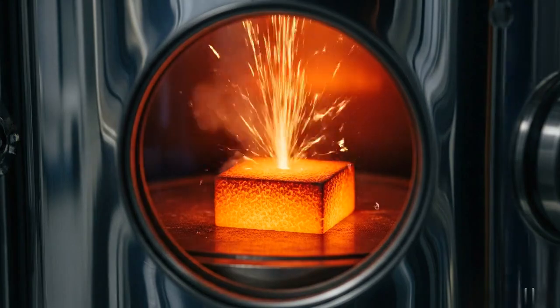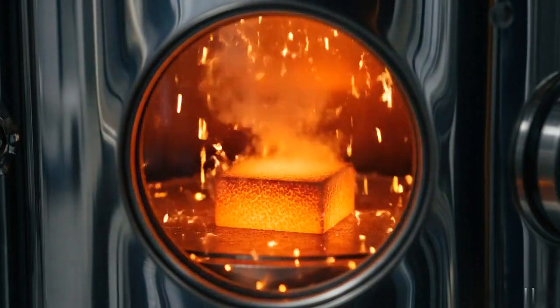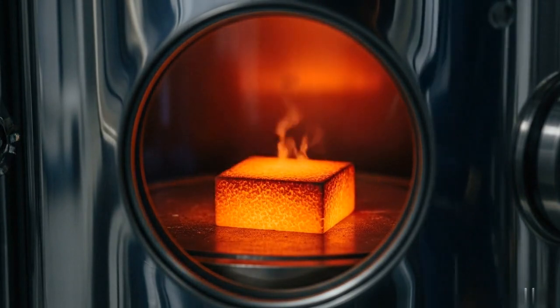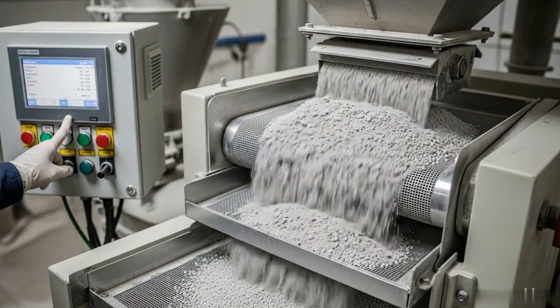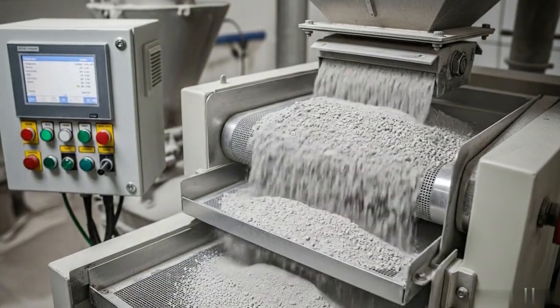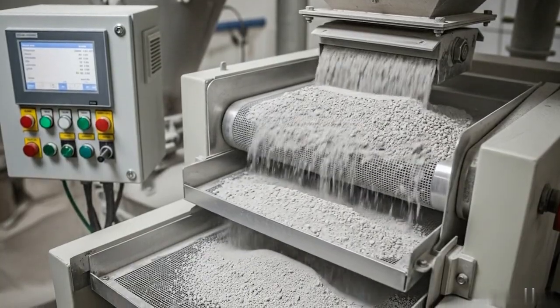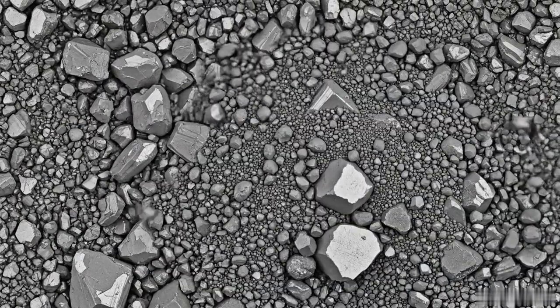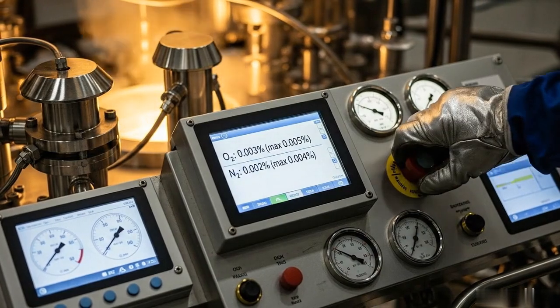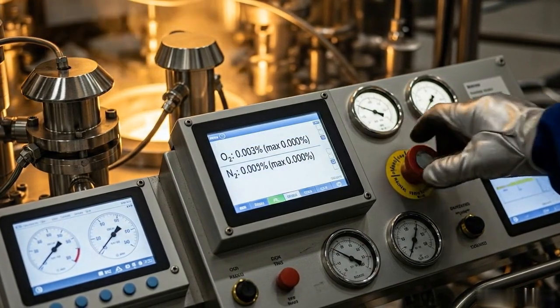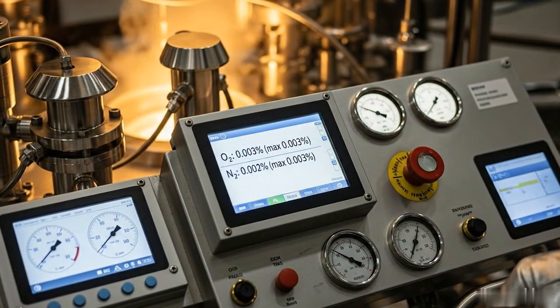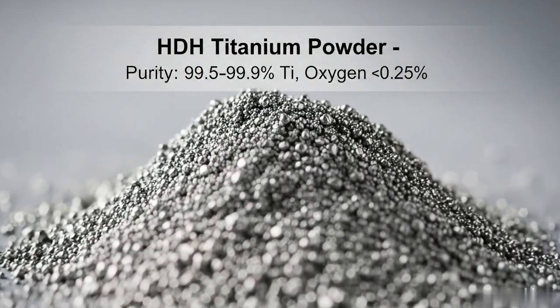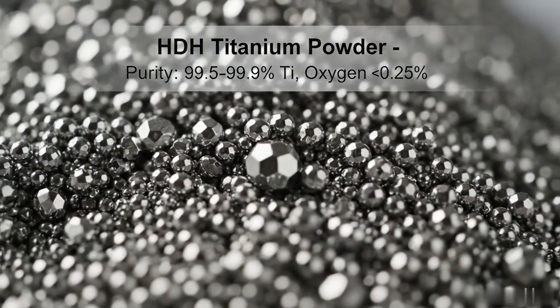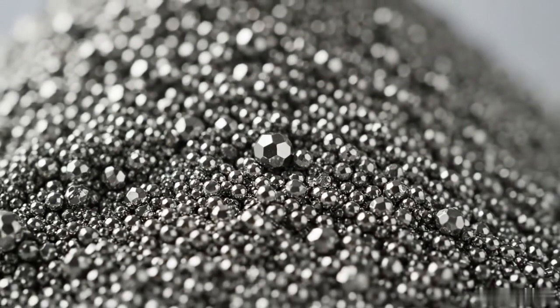Under high vacuum and temperatures of 600–900 degrees Celsius, hydrogen is driven off, converting the hydride back to ductile titanium metal. The resulting dehydrated powder is screened and classified to achieve desired particle size distribution. HDH powder typically has irregular, angular morphology with good flowability after additional processing. Oxygen and nitrogen pickup is carefully controlled during HDH to maintain low interstitial levels. Final HDH powder purity often reaches 99.5 to 99.9% titanium, with oxygen 0.25%.